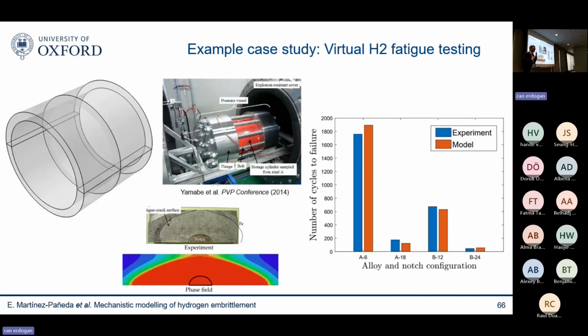And last but not least, there's some experiments done in Japan on full-scale tests when you have the full pressure vessel that fails after tens of thousands of cycles or thousands of cycles. They did it for 2 types of alloys and 2 types of notches. And again, you can see the model is able to predict very nicely, in good agreement with experiments, the behavior of a full-scale component over thousands of cycles. So I think this is a good sign that the model is mature enough to be applied to engineering practice.